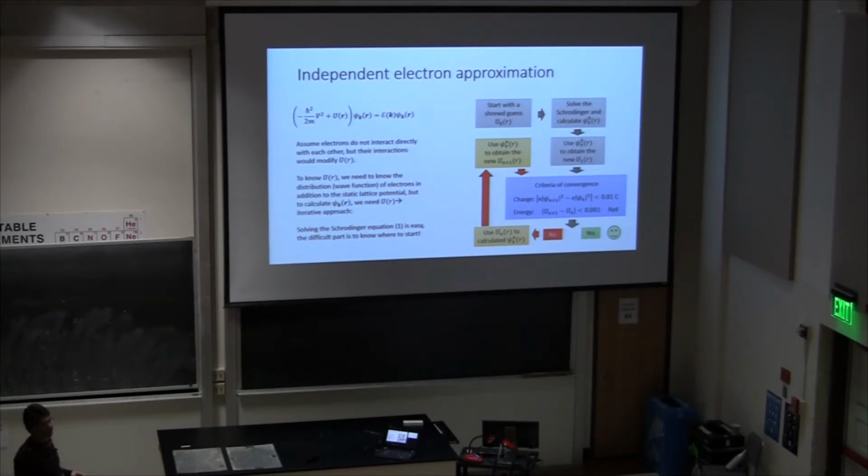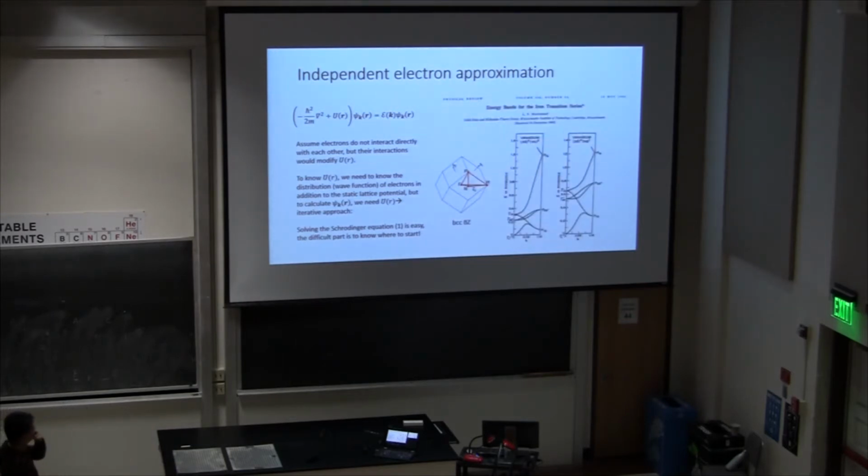So this is maybe the first thing I want to say about all these DFT computations, is that you have to really take them with a grain of salt. The methodologies are correct, the computations are correct, you're solving iteratively an equation, but the end result usually starts with a guess, and that guess can really set the course of the outcome of the computation. And it can happen that if your guess from the beginning was really far from reality, then you could end up in a completely wrong place. So DFT results are interesting and typically included in many publications, especially by material experts, but we all know that they have to be taken really with a grain of salt, and you cannot always just take them as a given.